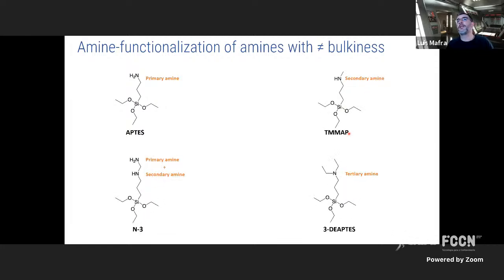So first, we were curious about many papers saying that when you change the bulkiness of the amines, you have radically different species that are formed, and the materials present very different properties. So we took the liberty to functionalize our silicas with these 4 amines that are very different in terms of chemistry. So we have a primary amine here. We have a secondary amine, then a diamine, which has a primary and secondary amine, and you have now a very bulky amine, tertiary amine, which should not chemically bond CO2.